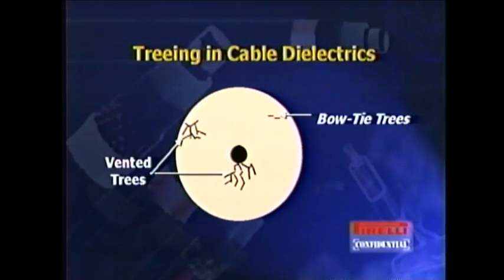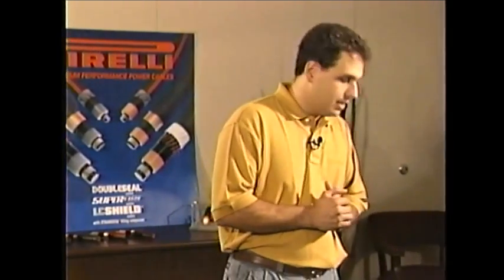There are two different types of trees that are commonly referred to. One is called the bow tie tree, which usually starts somewhere in the insulating material itself and is usually initiated from some type of a contaminant or something in the extrusion process that just wasn't right. We'd like to have an ideal extrusion process with medium voltage cables, but unfortunately that's not always the case. Bow tie trees in and of themselves are not huge problems as long as they're fairly small and there's not a high density of them. However, if they get very large and there are a lot of them, it can be a problem over time.